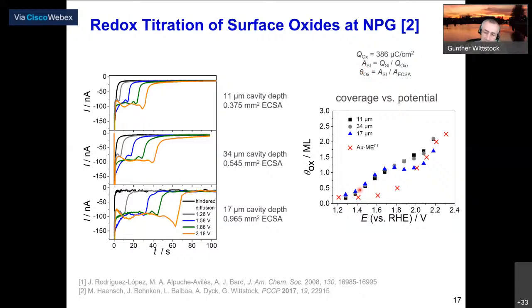And you see here, these are curves. Each of the symbols refers to one particular electrode. And then this was repeated for each of these experiments. The red crosses are made for an ultramicroelectrode, and they are data from literature, so they are not from us. And you see there's a very good agreement at high values, at low values, and here in the middle there's something which we don't yet understand, but which is very reproducible and may have to do with the special structure of this nanoporous gold.